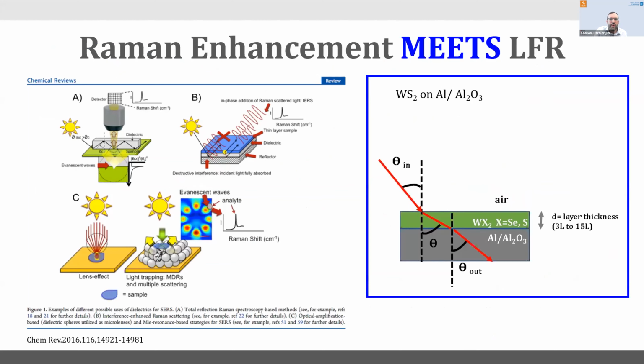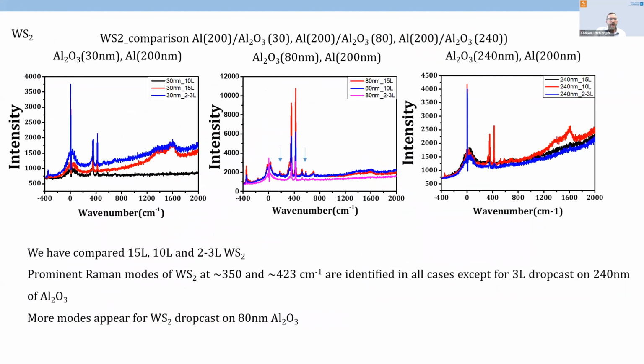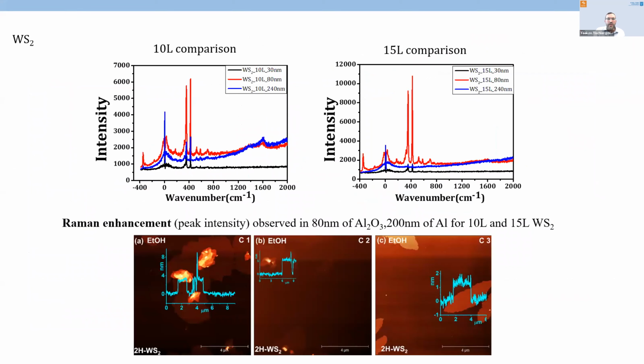always in Raman, because it's a photon starved process, we're looking for enhancement methods. We found that we can actually enhance low frequency Raman using dielectric structures. So here's an example of tungsten disulfide and different structures actually show significantly enhanced Raman scattering.